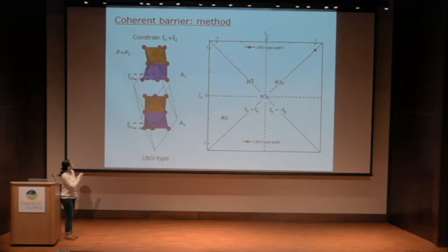Taking lithium niobate as an example, we know that the small A cations like lithium need to move downward. So we define these two distances, C1 and C2, and we plot them in this parameter space. At the ground state, those two are the same, so they are on the diagonal line with high symmetry R3c.